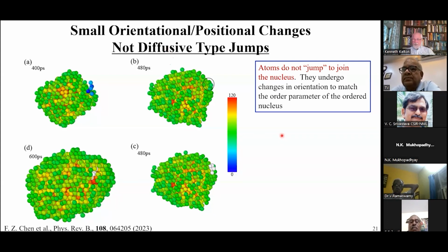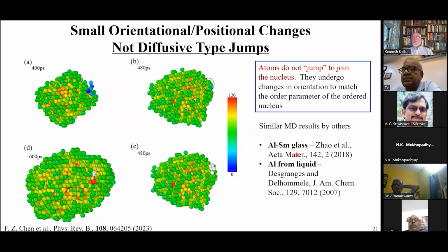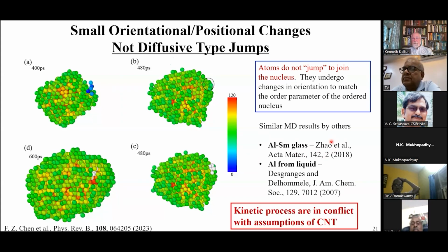This has been observed in these studies. It's also been observed in other MD studies. And collectively, what they say is that the kinetic processes are in conflict with the assumptions of the classical theory. So taken together, basically all of the assumptions in the classical theory are incorrect. We know how to accommodate the diffuse interface. The diffuse interface theory actually works quite well. We don't yet know what the consequences are of this change in kinetics. It may not be evident. It may be that those subtleties you can't see, but at least fundamentally, those assumptions are highly questionable.